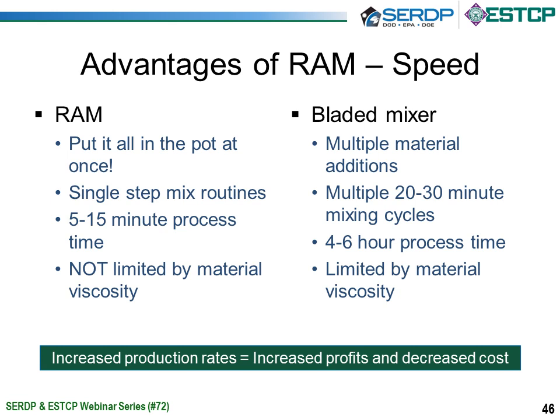A bladed mixer, for safety reasons, has incorporated into its mechanical workings things like shear pins, but if the material gets too thick, the shear pins break and the blades stop mixing. The RAM, on the other hand, on the left-hand side of your slide, you can put all the material in the pot at once.